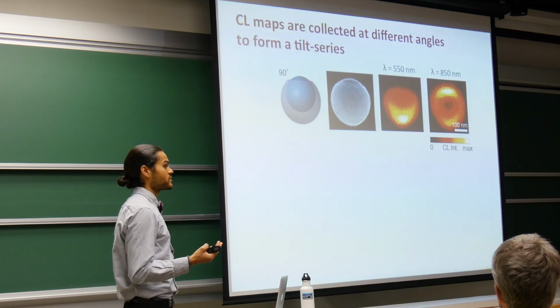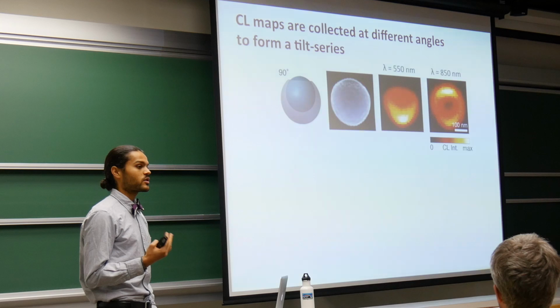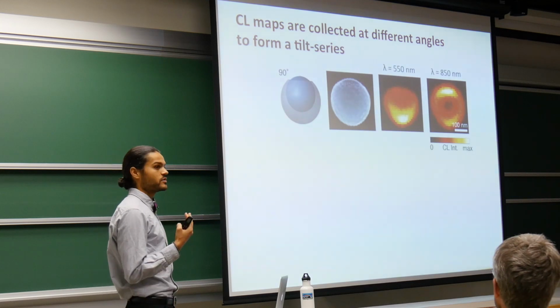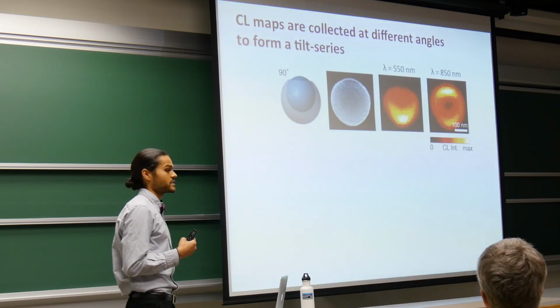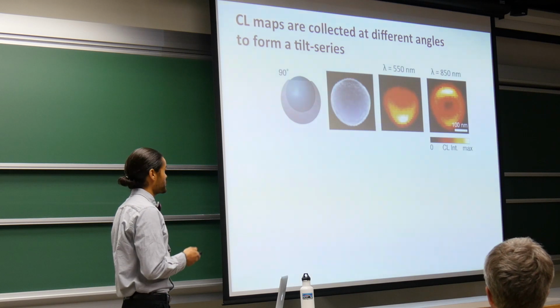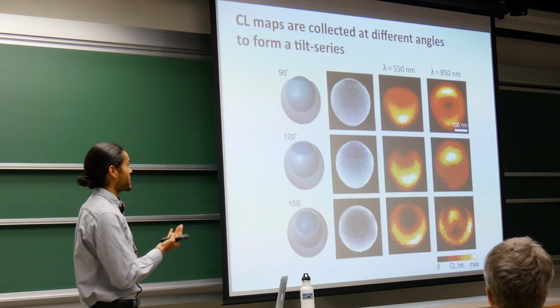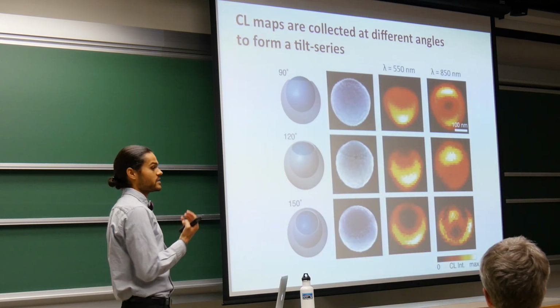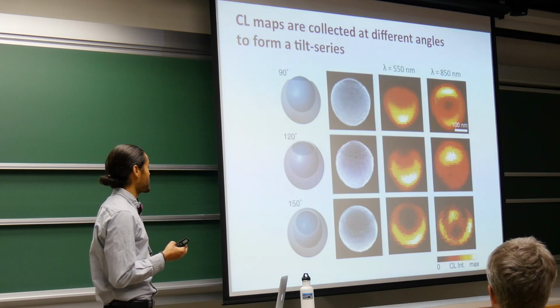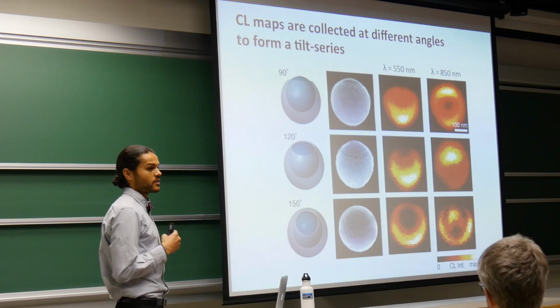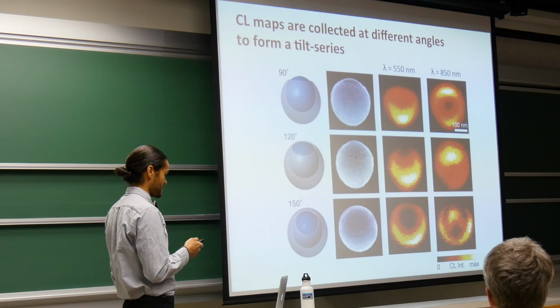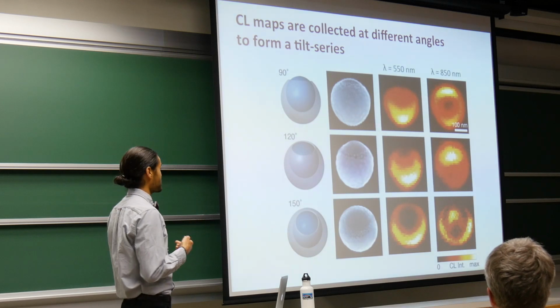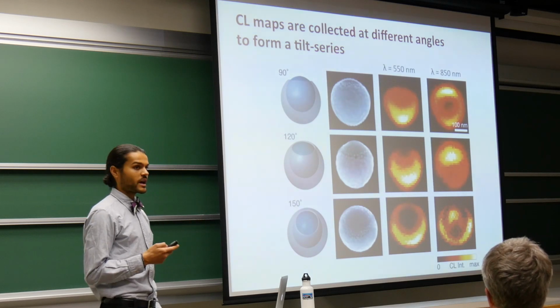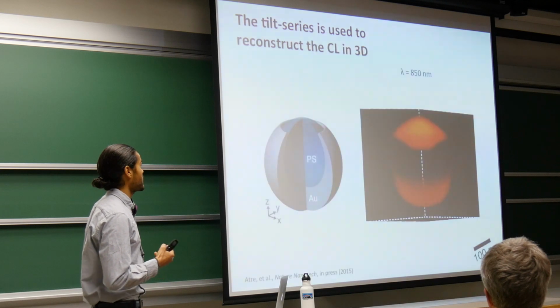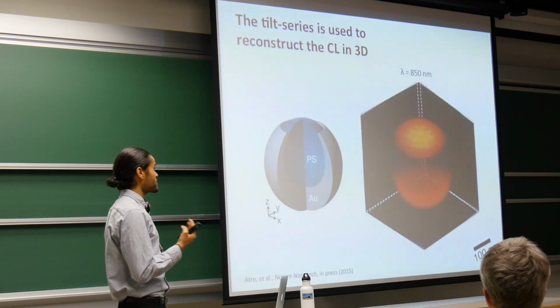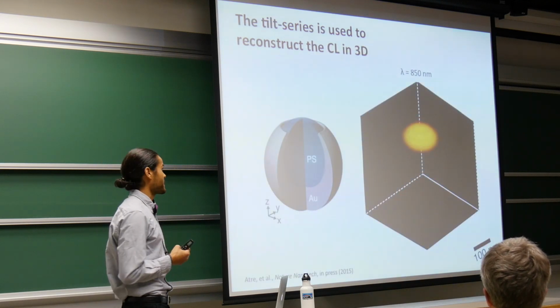We want to be able to reconstruct a three-dimensional function, and that requires us to have two-dimensional projections of the function at different angles. So what we do is we build up a tilt series, and by tilting the crescent and taking these CL maps in 2 dimensions at each angle, here I'm just showing 3 out of 14 angles that we collected, and by combining these tilt series together using a process called filtered back projection, we can create a 3-dimensional reconstructed image of the CL signal.